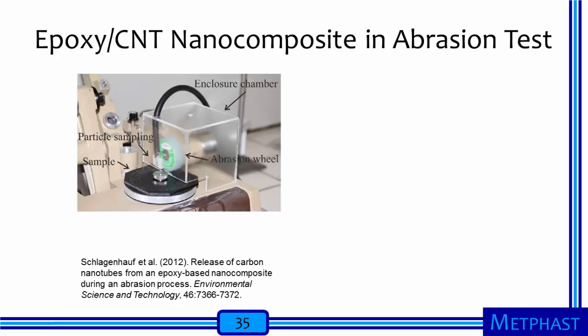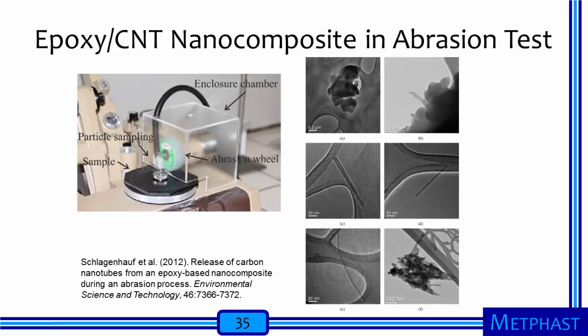Another research team has also shown the potential for release of free nanotubes. Schlagenhauf and co-authors set up a test apparatus where a wheel abraded an epoxy carbon nanotube composite plastic inside a small enclosure. The air inside the chamber was sampled near the abrasion wheel. Transmission electron microscope images of particles sampled from the air included agglomerated particles of epoxy resin, agglomerated particles with protruding carbon nanotubes like those observed by Wong et al.,